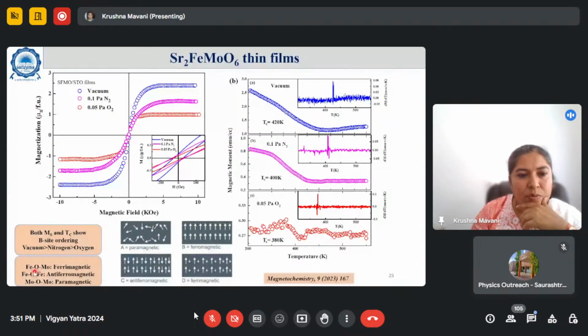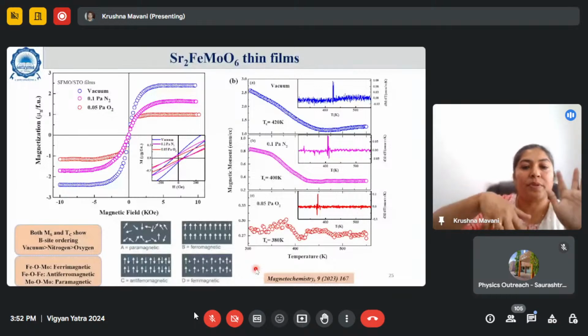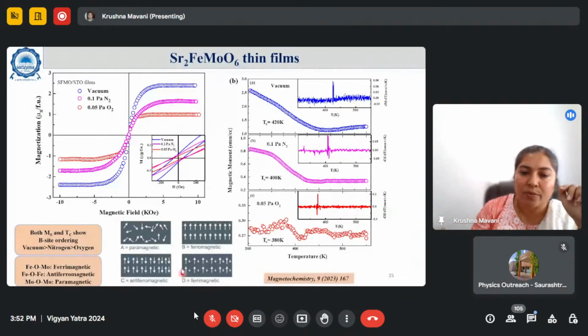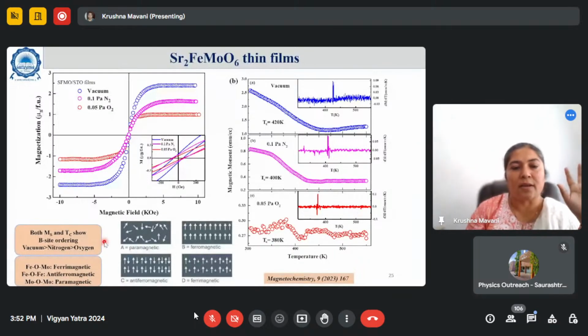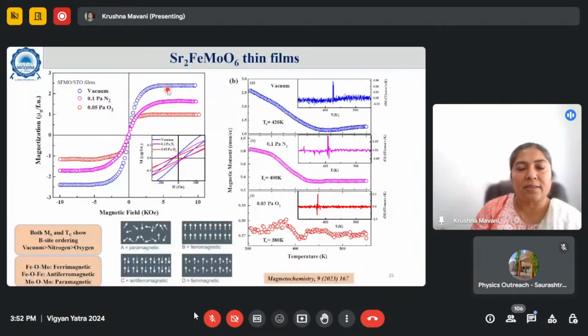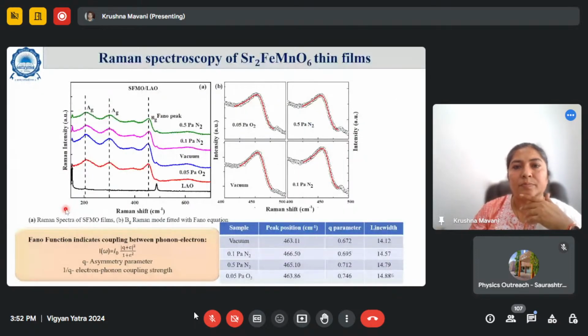The reason being Fe-O-Mo exchange is ferrimagnetic in nature. Ferrimagnetic means one sublattice having up spin, the other having down but unequal spin. So the compensating spin is smaller in size, and you have some net positive magnetization. This situation arises only when you have alternate Fe-O-Mo arrangement. Otherwise, it is antiferromagnetic or paramagnetic, which does not contribute so much to the magnetization. So it is a clear indication: the higher the magnetization, the higher the cation order. That we have observed clearly in our thin films.